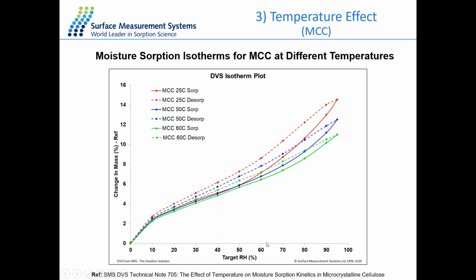Another observation is about the hysteresis gap between sorption and desorption. Here the red line is for 25 degrees, the blue line is for 50 degrees, and the green line is for 60 degrees. As the temperature increases, the water molecules move more freely out of the bulk structure, which results in a smaller hysteresis gap here, and also an increase in the diffusion constant in the previous slide.